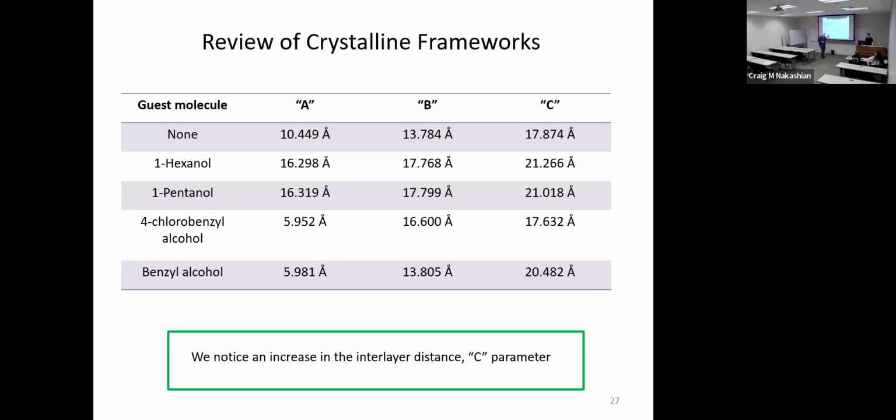Yeah. In some cases, we're seeing greater expansion than we typically would. In literature, a lot of the organic frameworks, when they place molecules in, may get half of an angstrom greater increase. And we're seeing upwards of almost 3.5 angstroms of space. Angstrom is that A with the circle on top, that's 10 to the negative 10 meter. So we're talking nearly three units larger in space of increase.